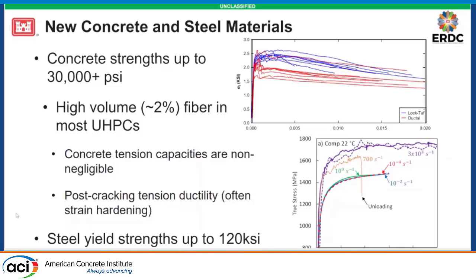But what I do want to point out, in yellow and purple, we have the high strain rate behaviors of these materials at 700 strain per second and 3,000 strain per second. So there is some preliminary data that does show some significant dynamic increase for these very high tensile capacity materials. Potentially problematic is that, actually that's not true. I was going to say that there was not enough ductility at the 700 strain per second, but it was actually unloaded rather than being fully tested to failure.